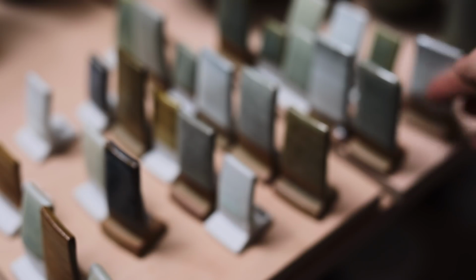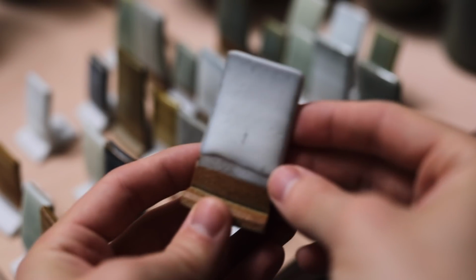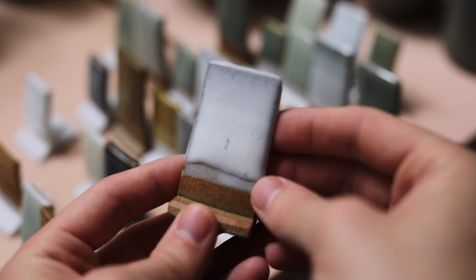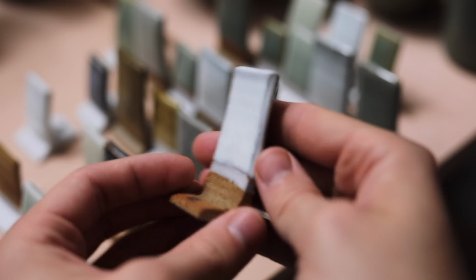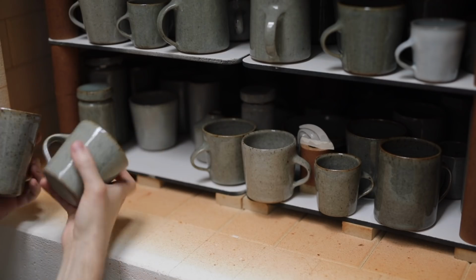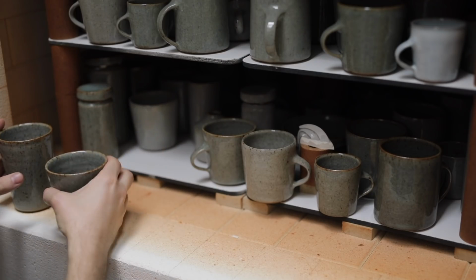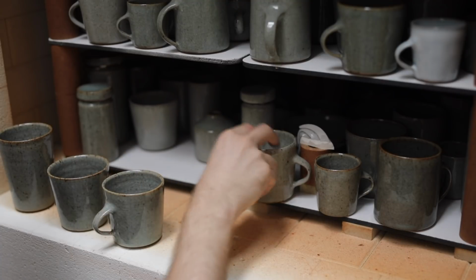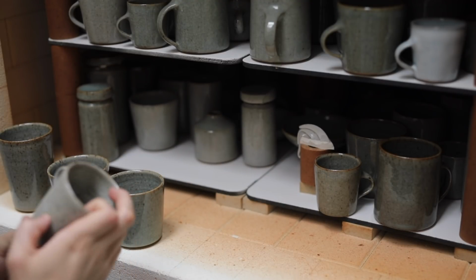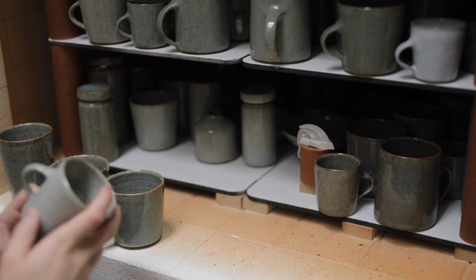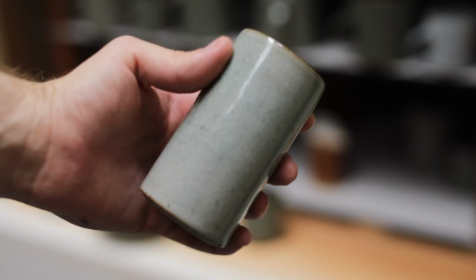And I had a few white bases which I was playing around with. These initial ones were okay, but there are some pinholing issues I need to figure out. Otherwise, the rest of the pots from the kiln were really good. Good colour, a very even firing temperature-wise, although there's always 1 or 2 underfired pieces from this bottom part of the kiln. And this is what that looks like.